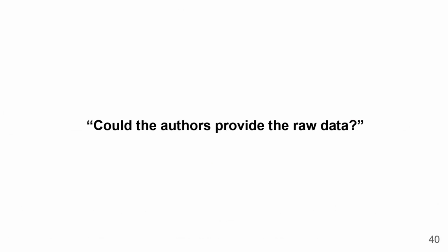So when we come across these, again, the best response is to ask the authors, can you provide the raw data? And most of the time, they can't. But in any situation where you have high frequency noise, be it an electroencephalogram or an X-ray diffraction pattern or an EDX spectrum, you can spot these data duplications without really even interpreting what the spectrum means. And you can know that something went wrong here.